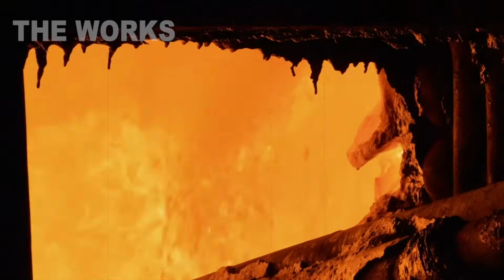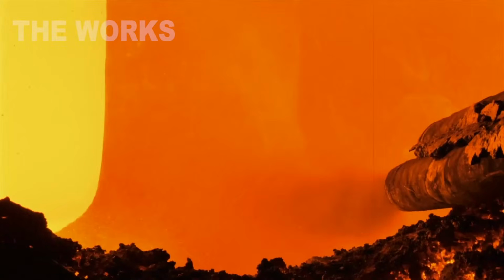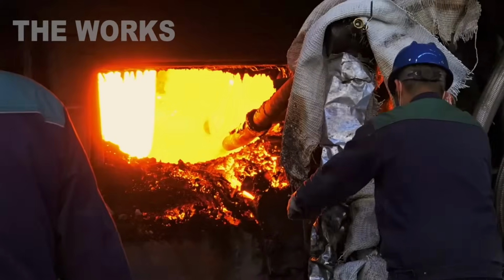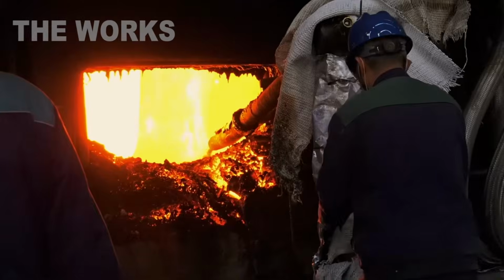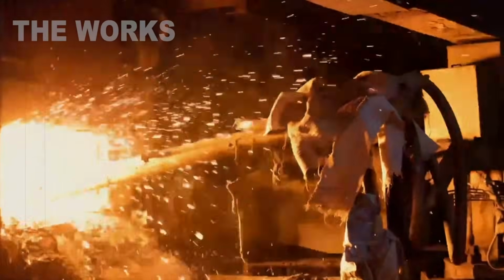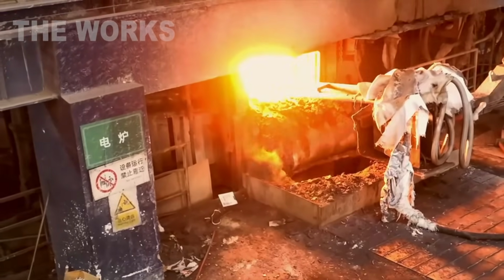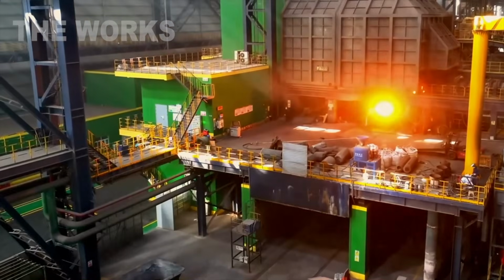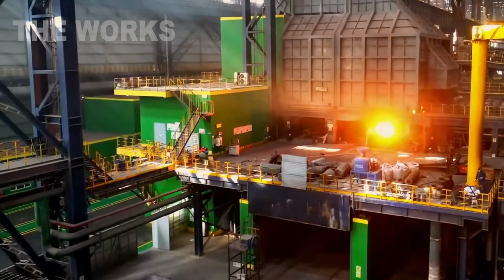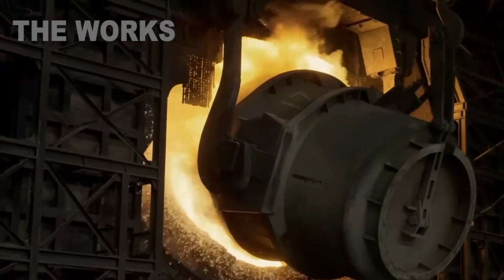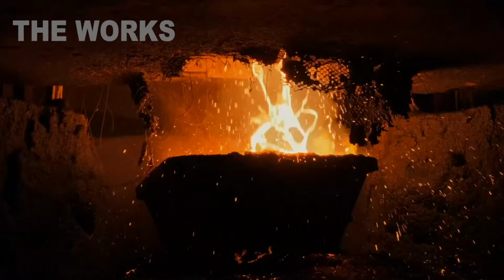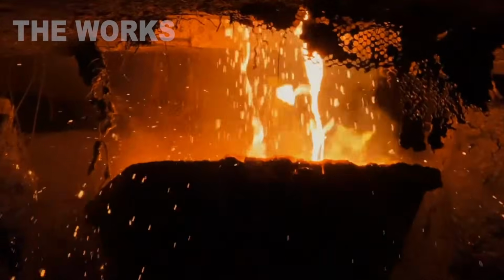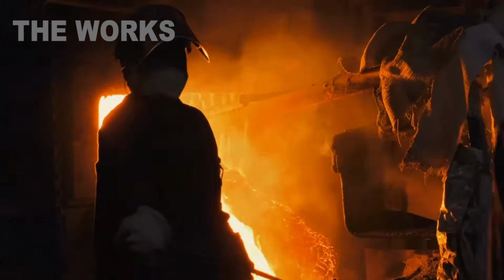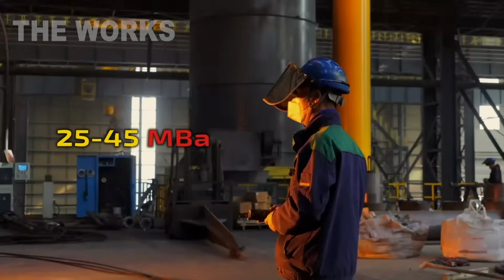Inside, real alchemy unfolds. Chromium ore mixed with coke melts down, oxygen escapes as carbon monoxide, and molten ferrochrome, an alloy of chromium and iron, flows to the bottom. This is a submerged arc furnace, and this is where most of the world's ferrochrome is born. The process runs non-stop. Fresh batches of ore and coke pour in from the top, molten metal and slag tap out from the bottom. A single furnace like this can pack 25 to 45 megavolt amperes of power.